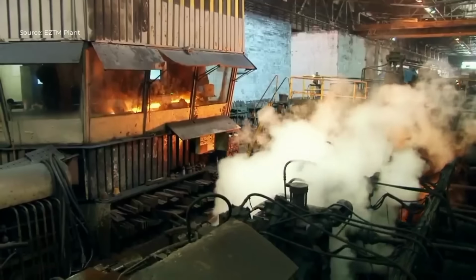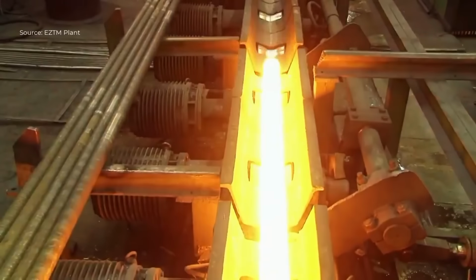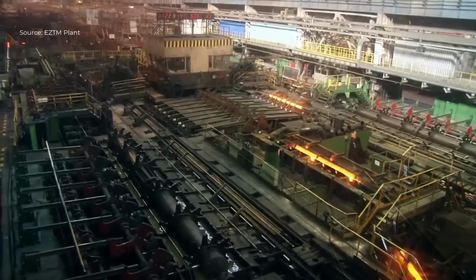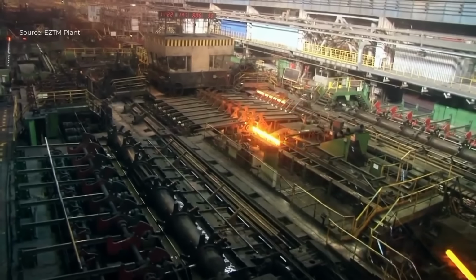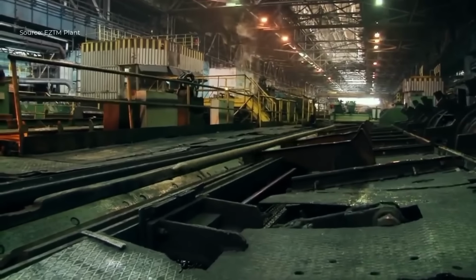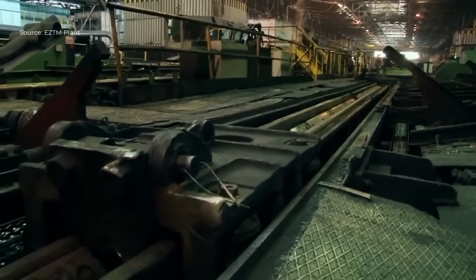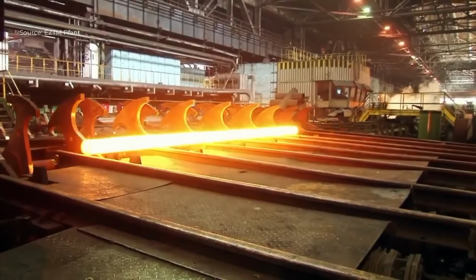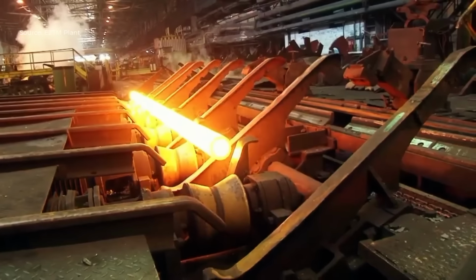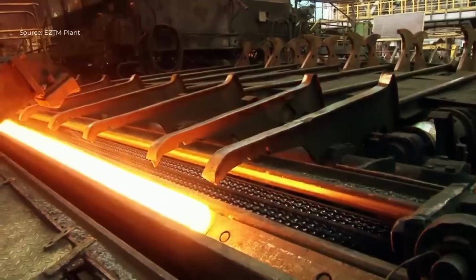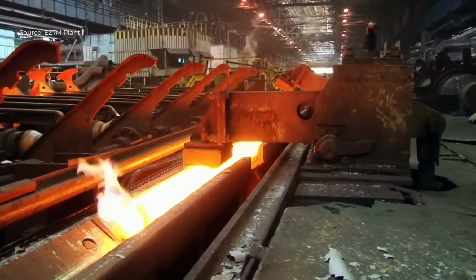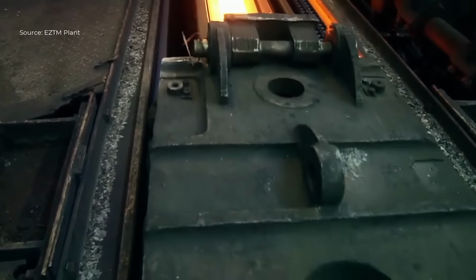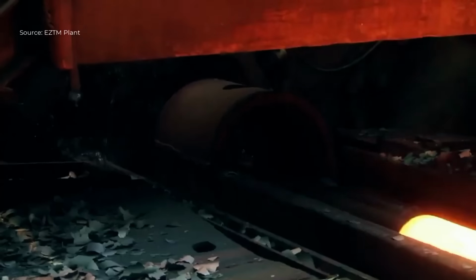Once the billets reach the desired temperature, they are fed into the TPC-1 rolling mill. This advanced mill operates on a continuous rolling-on mandrel principle, where the heated billet is pierced to form a hollow shell. The mandrel inside the rolling stand shapes the internal diameter, while the external rollers compress the shell, gradually reducing wall thickness and expanding diameter to meet the specified dimensions.